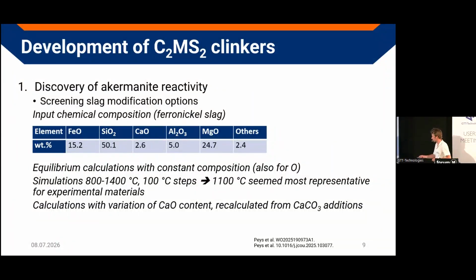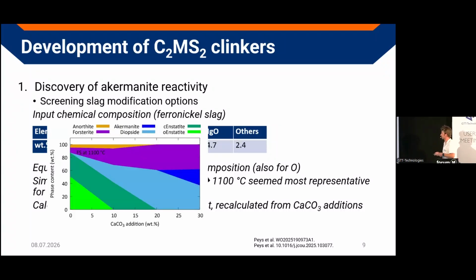We did some equilibrium calculations with a constant composition, but also with different calcium contents. We screened different temperatures, and then did it again for more calcium. And with increasing calcium addition, we can see that the phase composition changed, of course.